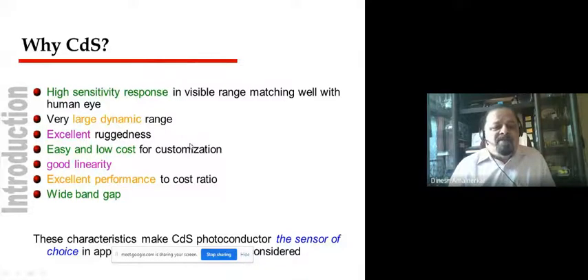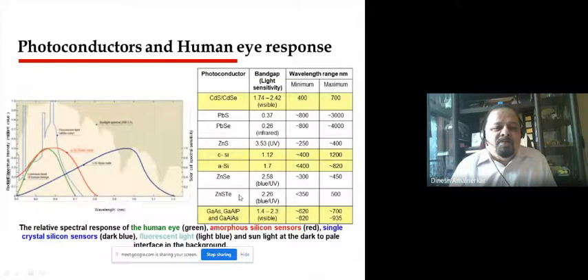It has a very large dynamic range of operation. It has excellent ruggedness, easy and low cost customization, good linearity with respect to applied voltage and intensity of excitation, an excellent performance to cost ratio, and a typical band gap of 2.4 electron volt, which is good enough to add some interesting dopants and make it more photoconductive. So all such characteristics make cadmium sulfide a photoconductor sensor of choice.